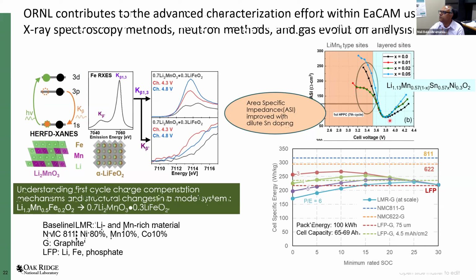In this region, which is shown in blue here, sites which are in the layered component of this material are active. And in this region, it is sites which are in the Li2MnO3-like regions which are active. So it is LiMn6 type sites, and these are the layered sites. It is clear that in the layered region, the area-specific impedance is consistent with what we would see for any conventional material. However, for the x equal to 0 sample, the area-specific impedance shoots up, which suggests that this material will not be able to deliver energy at a high rate of extraction of energy in these lower voltage sites.